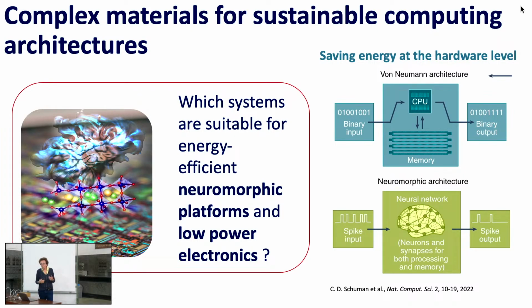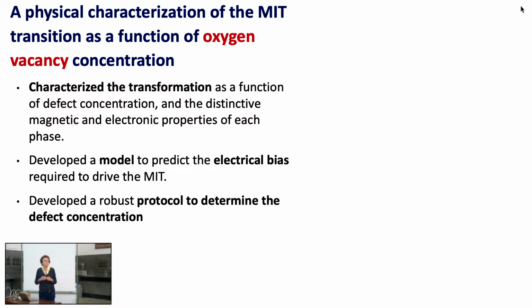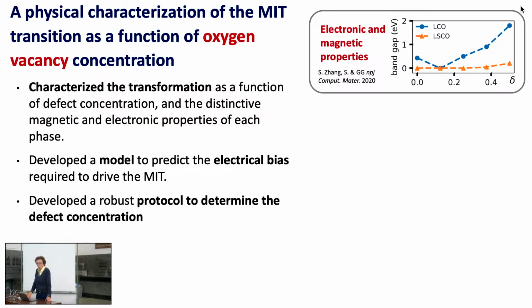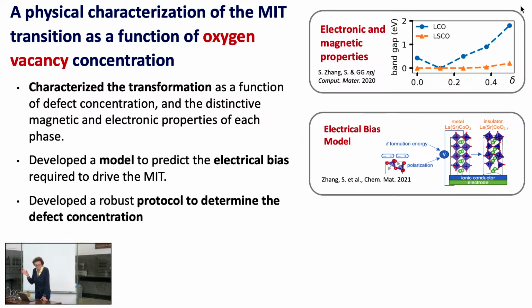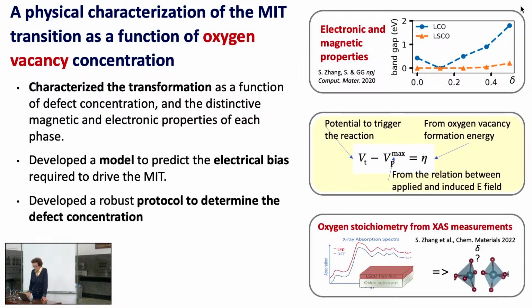How do you realize this? One way to realize this is to take some transition metal oxides and change the number of oxygen vacancies in the oxide. And how do you change it and how do you move it with a small bias? So we have studied this to characterize the transformation of our system. We have also understood electrical bias models, and this is very, very important. We have worked with the experimentalists to compare spectra that we computed with what they measured, to convince ourselves that we were looking at a realistic material.